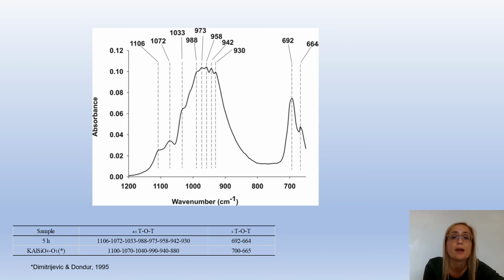This is the infrared spectrum, which shows 8 partially resolved bands that can be identified in the high frequency portion of the spectrum. These bands are due to the T-O stretching vibration. 2 additional bands with lower shifts are evidenced, which are similar in frequency to those observed by Dimitrijevic and Dondur, who interpreted them as being due to symmetric T-O stretching modes. It is more likely that these lower frequency vibrations are due to K-O stretching motions, as its bond strength is weaker than that of the tetrahedral T-O bond.